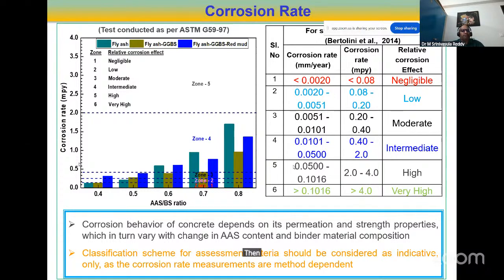Then corrosion rates. Corrosion also increases with the increasing AS to BS ratio. We can observe the least affected are the concretes with low AS to BS ratio, and the highly affected are the concretes with high ratio. But everything, maximum, is nothing abnormal. Everything is below intermediate, moderate, and we can say negligible also. In Zone 1, for fly ash and fly ash GGBS, I noticed negligible corrosion.